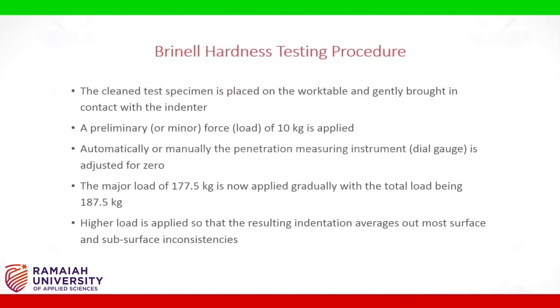The cleaned test specimen is placed on the work table and gently brought in contact with the indenter. A preliminary or minor force, that is load, of 10 kg is applied. Automatically or manually, the penetration measuring instrument dial gauge is adjusted for 0. The major load of 177.5 kg is now applied gradually with the total load being 187.5 kg. Higher load is applied so that the resulting indentation averages out most surface and subsurface inconsistencies.